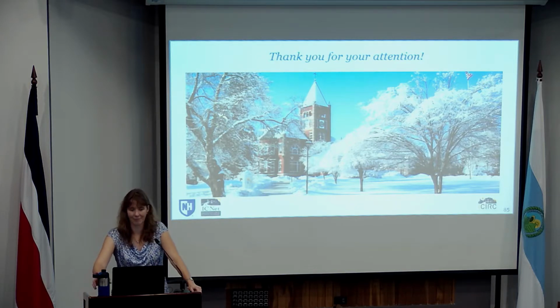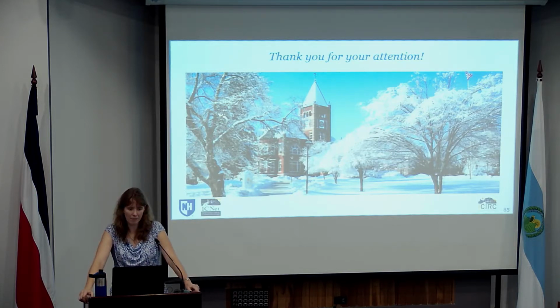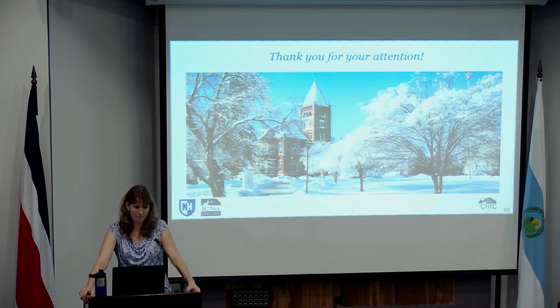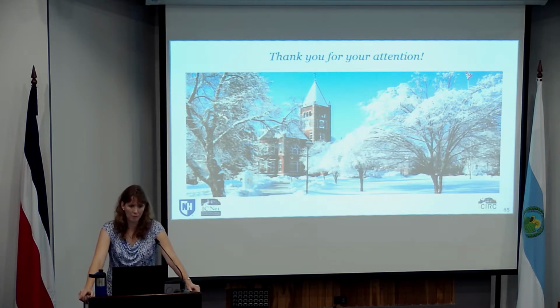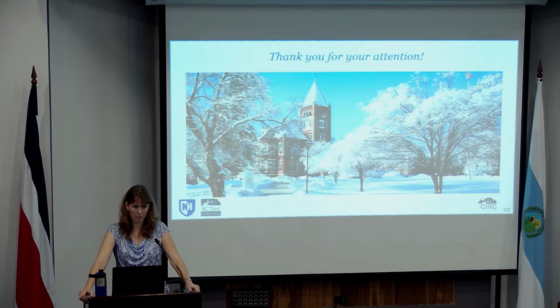I've done that work, and several other people have also looked at it. One thing they use is a weatherometer, which is a device used for roofing. You add UV light plus temperature plus moisture, and we've aged samples using that. The one thing that you see different is that UV penetration does a significant amount of aging to the asphalt mixtures. We've seen that taking samples from the roadway, but that aging done by the UV is just in the top 4 or 5 millimeters.